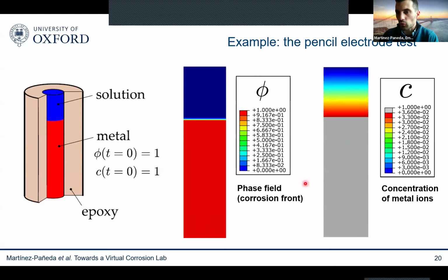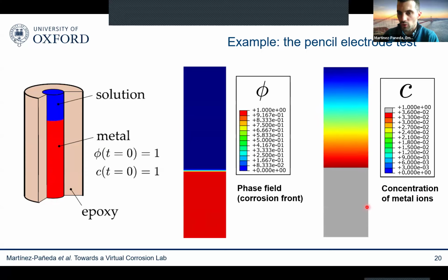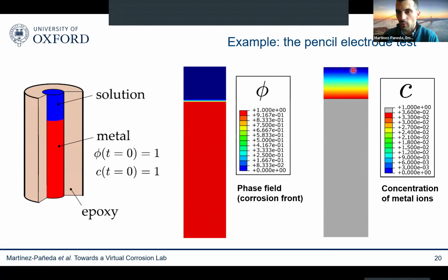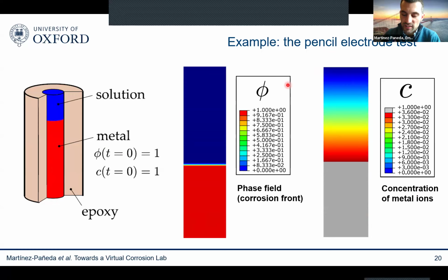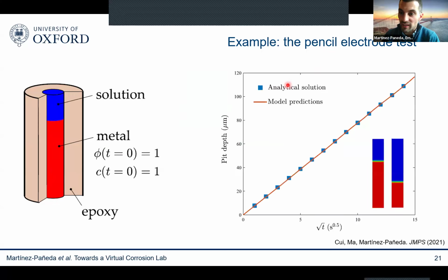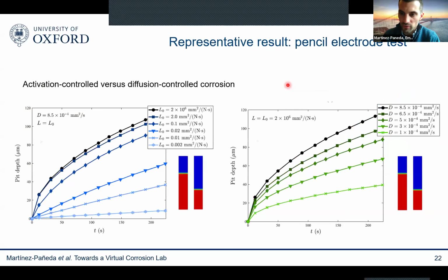And then on the right, you see the concentration of metal ions all the way from the saturation concentration to 0 far away from the electrolyte. And the good thing is that because this is a simple 1D problem, we have an analytical solution for the case of diffusion control corrosion. So we can compare the outputs of the model with that analytical solution, and as you can see, it agrees very well. We have also compared with experiments and it agrees quite well. But one aspect that I want to emphasize is that these models can capture naturally and very nicely the transition from activation control corrosion versus diffusion control corrosion that I discussed before.